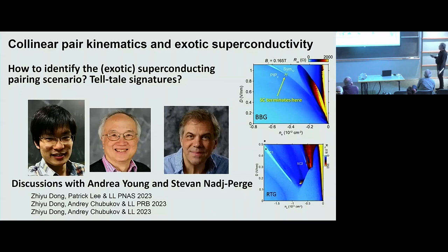right? And the idea comes from comparing phase diagrams. You can see it most clearly here in graphene bilayer and an ABC trilayer that Andrea talked about. And you see that, strangely, in graphene bilayer, the superconducting phase terminates abruptly at some point, whereas interactions and Fermi surface properties don't seem to change very much. You see that, and confirmation of that is that the interacting phases basically don't care. They change very smoothly, but the superconducting phase terminates abruptly.